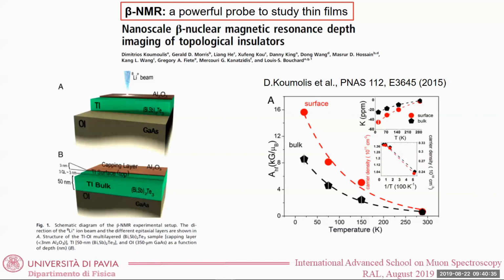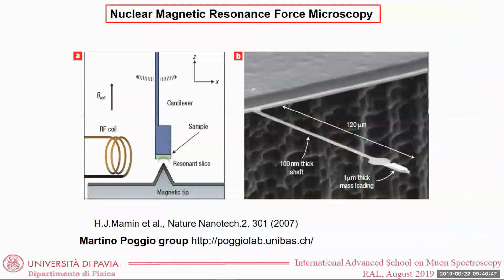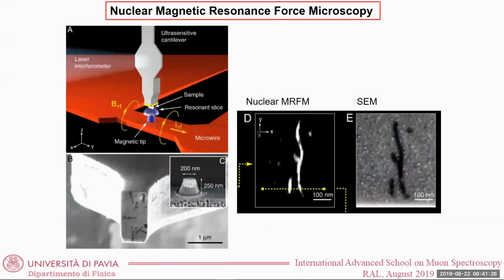Okay, this can be done with beams of muons, beams of nuclei. Can we do it with NMR? Can we do it with ESR? Well, usually not, but of course there are many advanced developments of NMR, for example nuclear magnetic resonance force microscopy, which is basically a nuclear imaging technique based on the use of a cantilever tip, where you have a sample at the end of the tip with your nuclei, you apply a radio frequency field, and you have a small magnet close to the end of your tip. In this case you can perform NMR experiments on something of the order of 10 nanometers thickness.